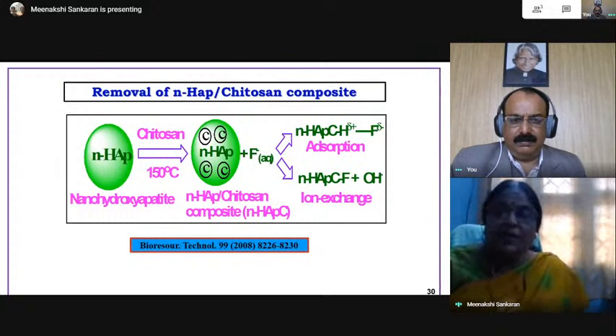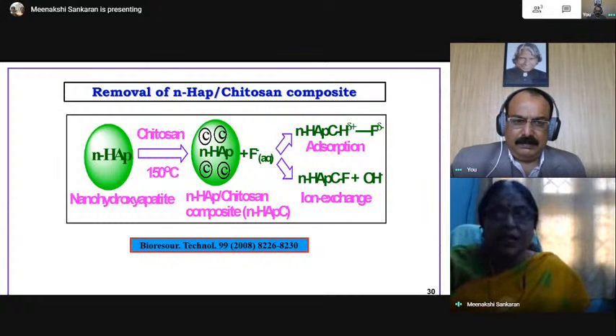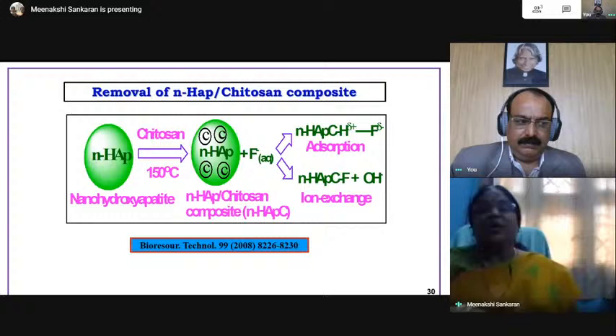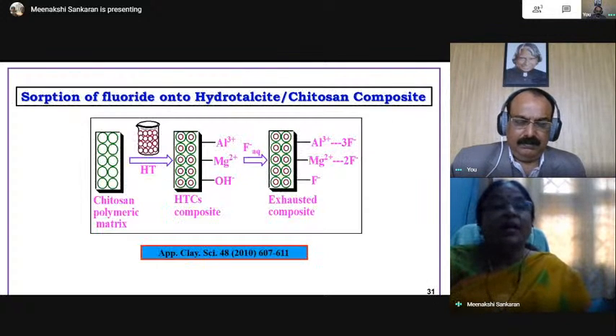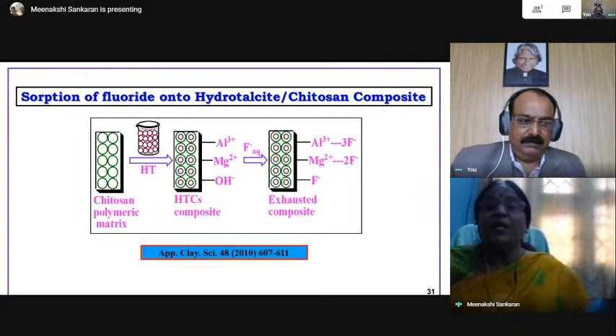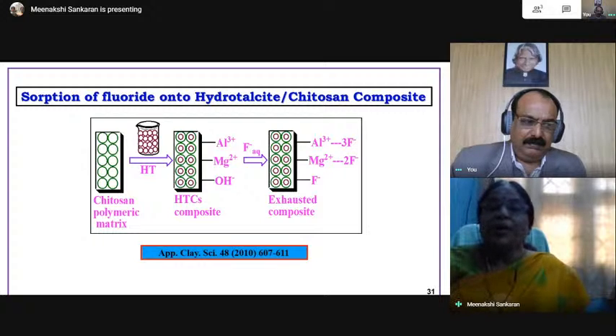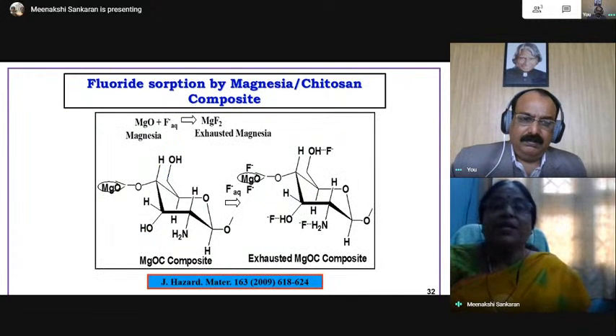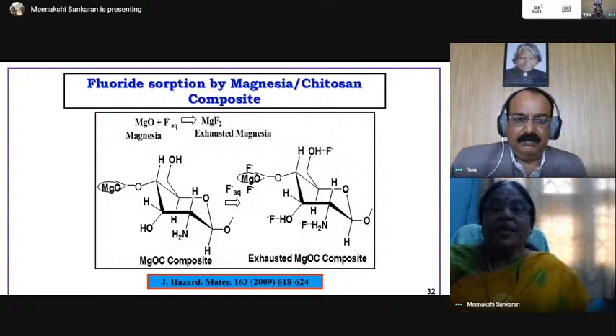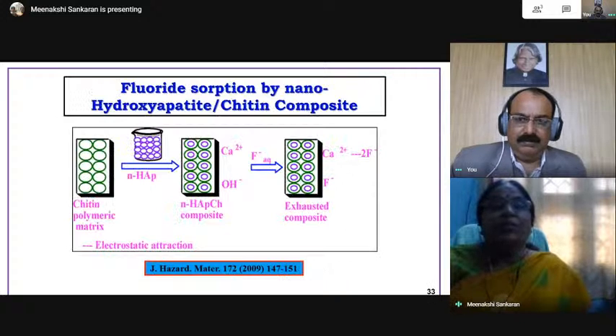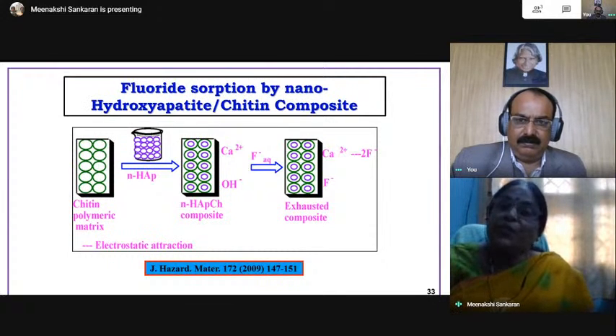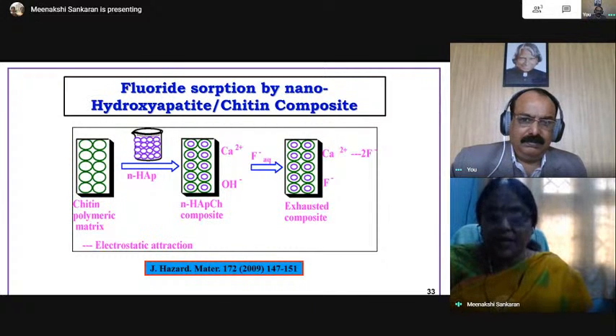So all the details are published. I have mentioned the journal in which it has been published, so for reference, people can refer to this. And hydrotalcite, again, is an inorganic material mixed with chitosan. Here also the composite material removed fluoride by ion exchange as well as adsorption. And we have used magnesia chitosan composite, and again the same mechanism is followed for the removal of fluoride. And with nanohydroxyapatite, chitin also, not only chitosan, is capable of removing fluoride. We have made chitin composites with inorganic material.